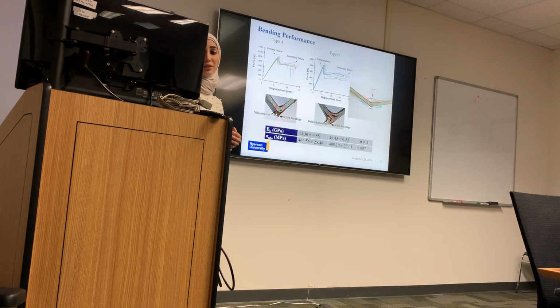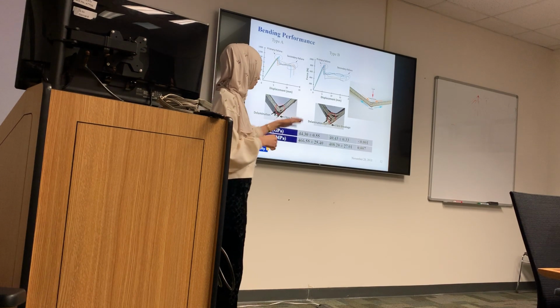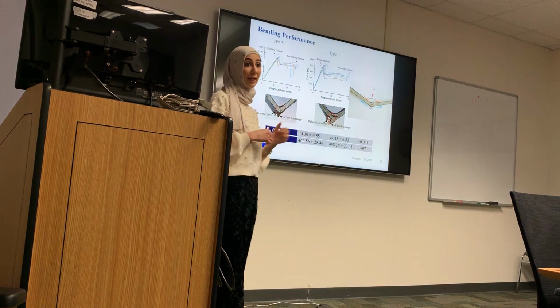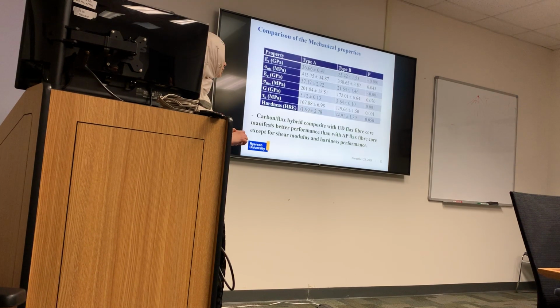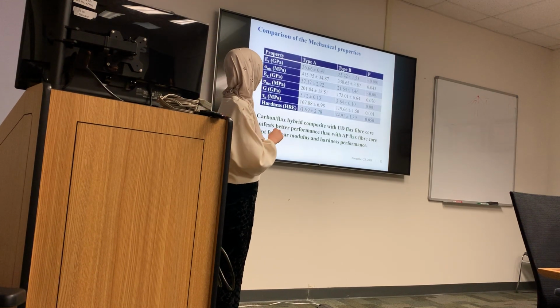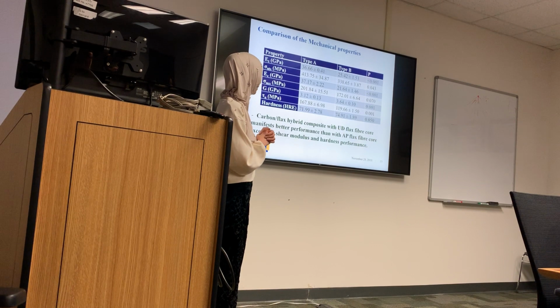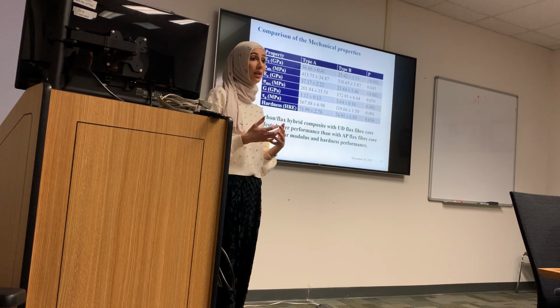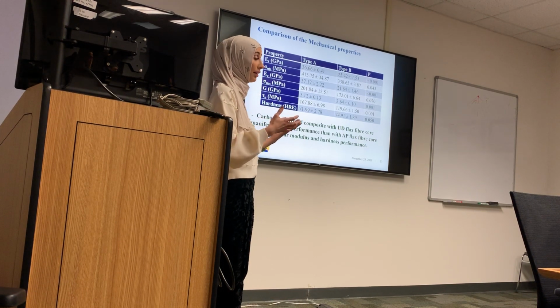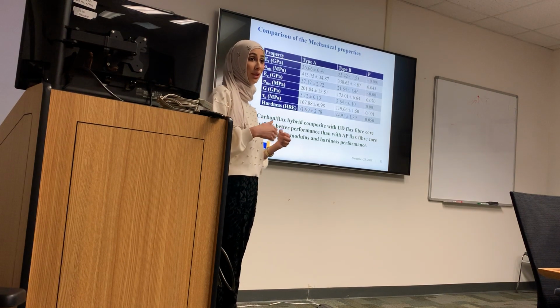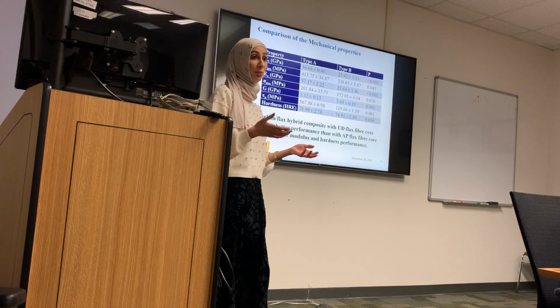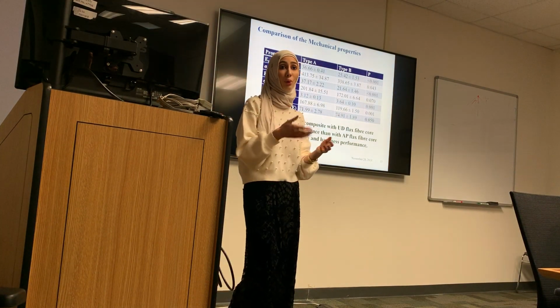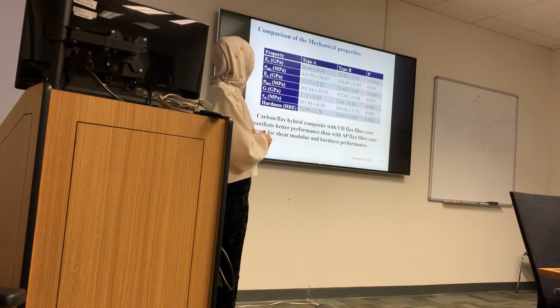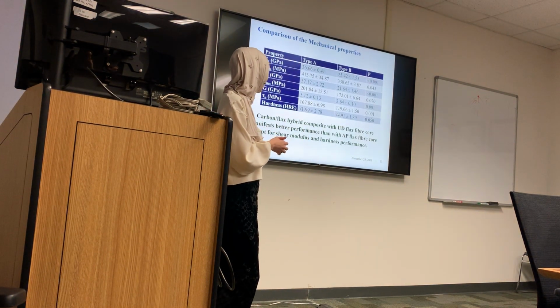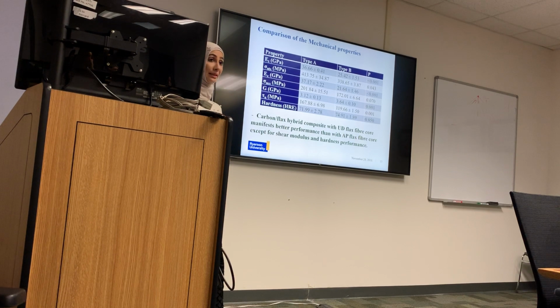We see here that the bending stiffness gives us between 40 to 44 gigapascal. If we compare the modulus for bending to the other moduli that we got from different mechanical characterization, we find that bending is the highest, because that's actually the mechanism of a sandwich structure: to provide high rigidity to the material with no weight added. The hybrid composite type A manifests better performance than type B.